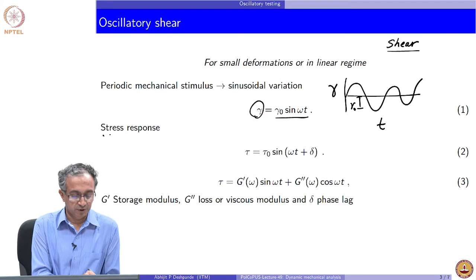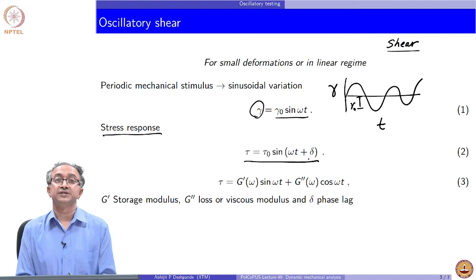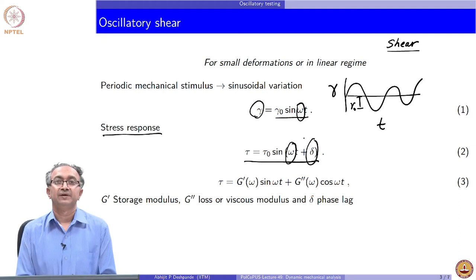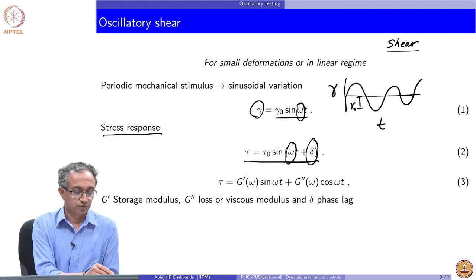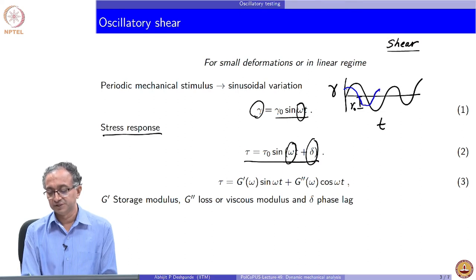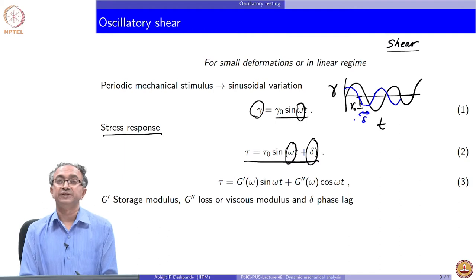The stress response, which is the measured quantity, is also sinusoidal. Because it is a linear response, the response is at the same frequency as the input. However, there is a phase lag. If we plot the response, we get a curve which is slightly shifted in phase and will be zero at different points. Therefore, there is a phase lag between the stress and the strain.